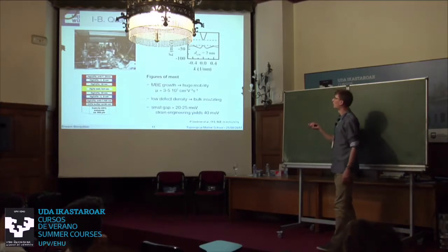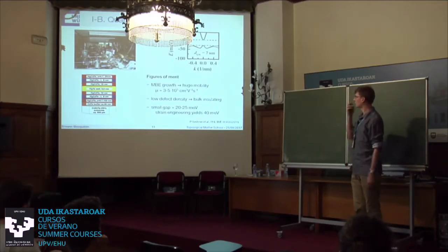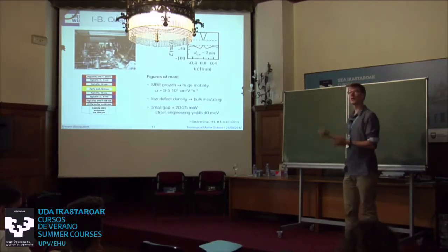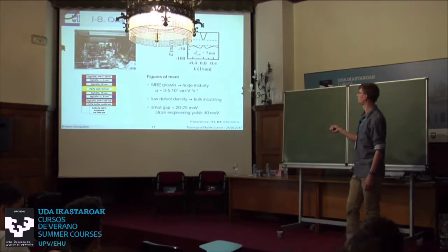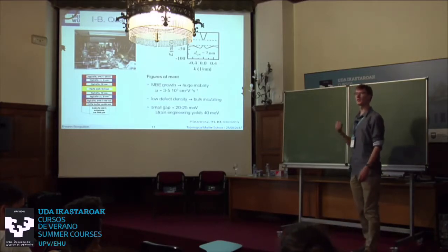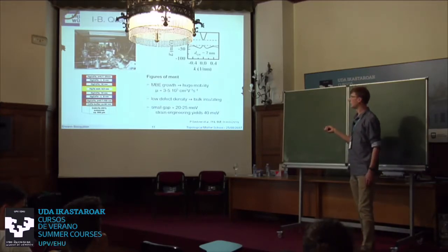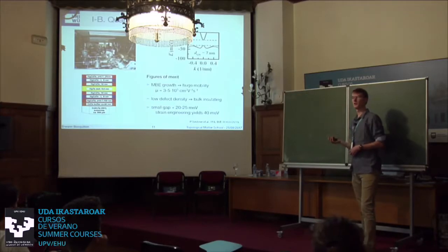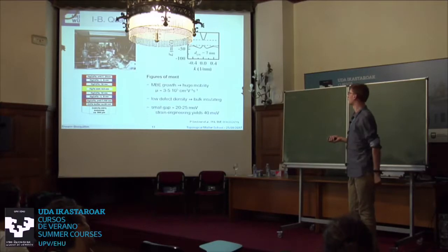And this is not a new technique. This has been used for I don't know how many years in gallium arsenide technologies and so on. But this is responsible for the very high quality of the crystals and their very good mobility. They have very low defect density also, which means that they have very low doping, and which means that naturally the bulk is insulating. You're very close to the gap. You're not deep in the valence band or deep in the conduction band, as you may have heard from the bismuth compounds, which means that you're very close to the gap and you have a very good insulating bulk.